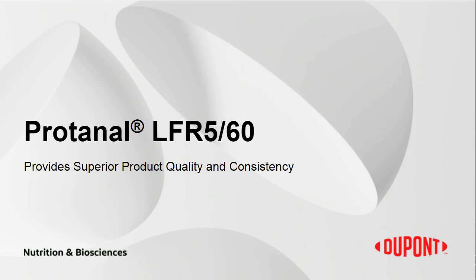Thank you, Matthias. Coming to Protanal LFR 5/60, DuPont produces different grades of sodium alginate for different applications, and this Protanal LFR 5/60 is the sodium alginate grade used in anti-reflux suspension formulations. It is a low molecular weight sodium alginate extracted from the stem of Laminaria hyperborea, which is harvested and produced in Norway. These grades of sodium alginate have a high content of G blocks with high gel strength.